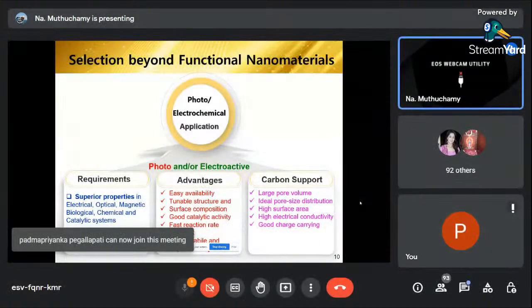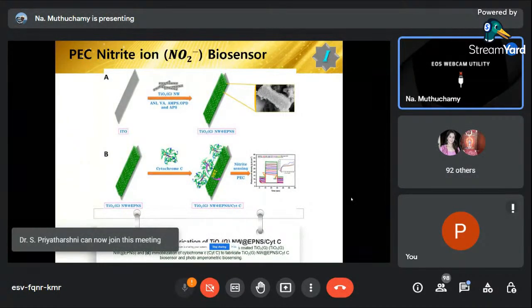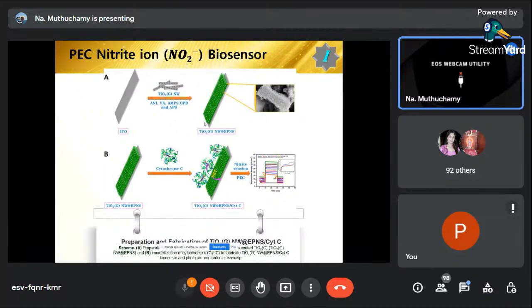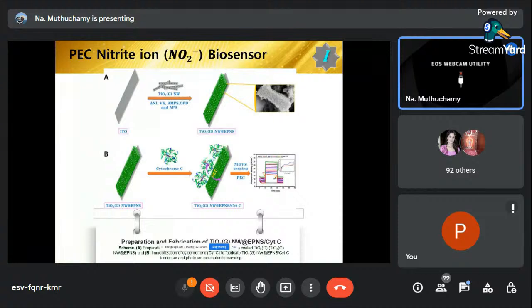Due to these properties, we select a good candidate for photoelectrochemical sensors and other sensors. The first one is in this work, a novel photoelectrochemical biosensor platform discovered by modifying graphene with an electroconducting polymer nanosponge and TiO2 nanowire. First, the TiO2 nanowire is prepared by the electrospinning method. After that, we modified it with polymerization to make a polymer nanosponge. The inclusion of graphene and TiO2 nanowire in the electropolymer nanosponge, along with immobilized cytochrome C, proves the basis for the construction of a highly sensitive and selective photoelectrochemical biosensor for nitrite ion. So these are the main roles.